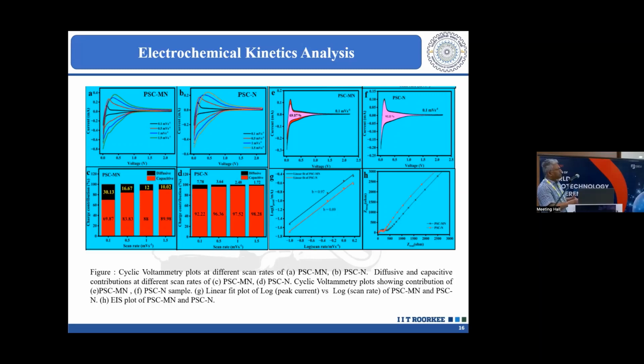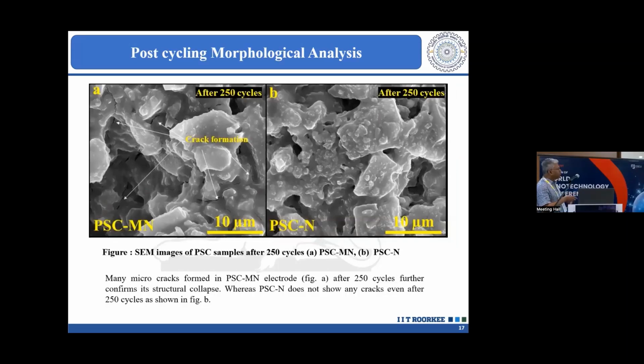And this is again the conductivity measurement. So for two materials, conductivity by EIS measurement, electrochemical impedance spectroscopy studies. And then this is what we try to find out, which one has a higher conductivity. And then what happens is that the cells have to be tested for a large number of cycles.